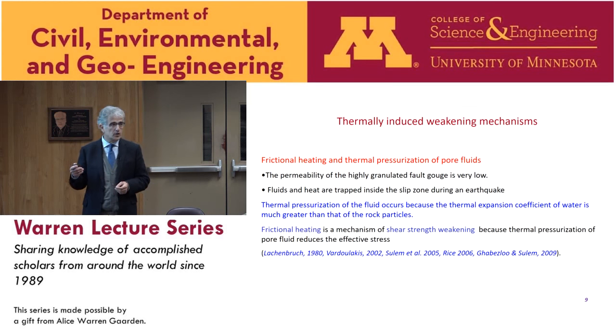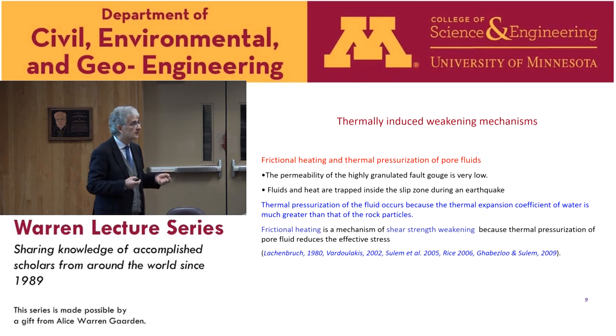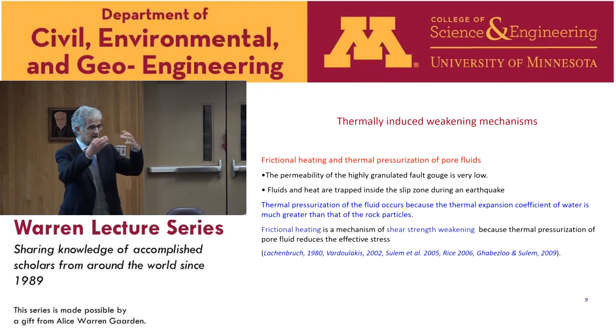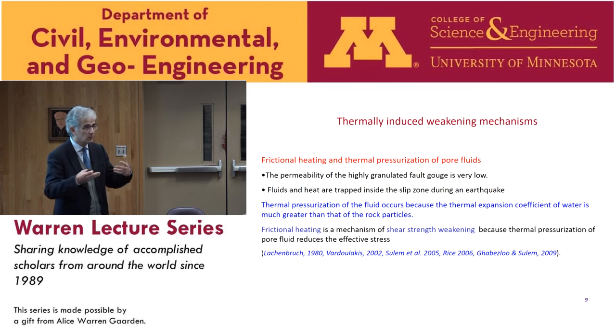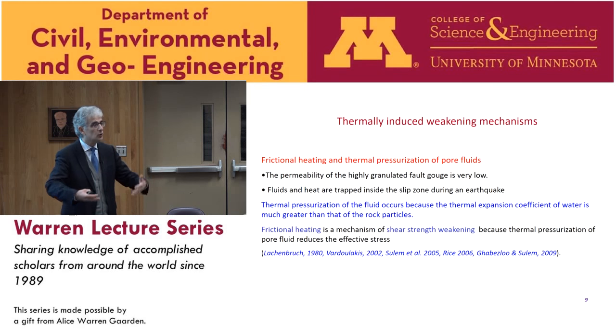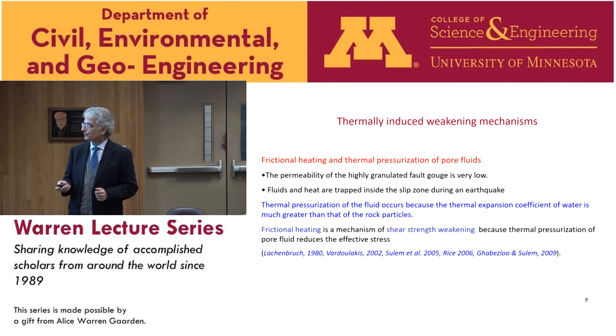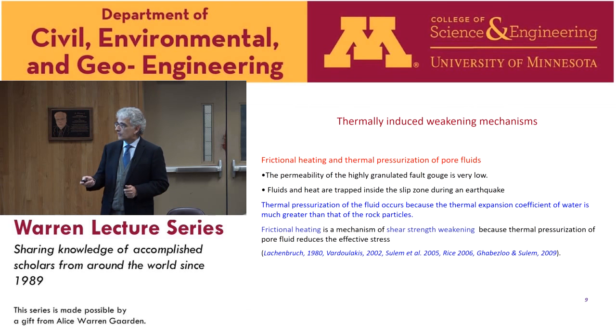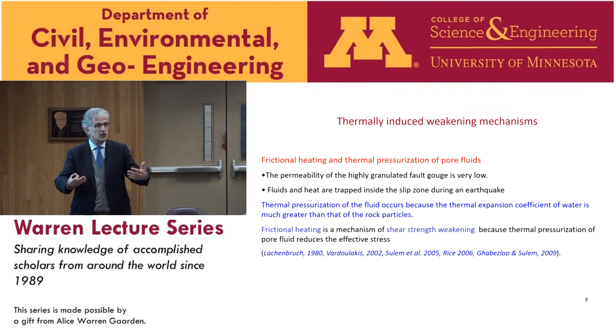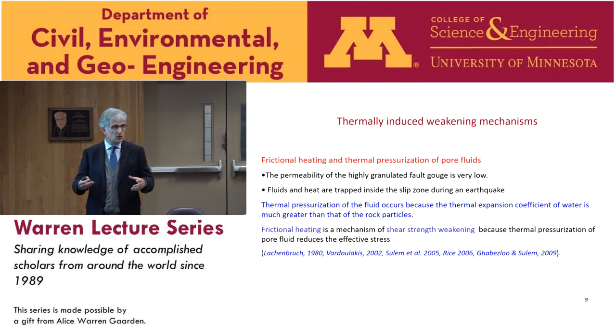This mechanism of thermal pressurization of fluid is also important in other domains of geomechanics, for example, in deep repository of radioactive waste, for which we know that these are exothermal materials which heat the rock mass. For example, in Europe and also in France, we have some projects of repository in shale or in deep clay rocks formation. The problem of putting hot waste into a rock mass with very low permeability can induce an increase of the pore pressure that we have to pay attention to in the design. So of course, thermal pressurization is a mechanism of weakening because the effective stress is decreasing, so the shear resistance is decreasing.